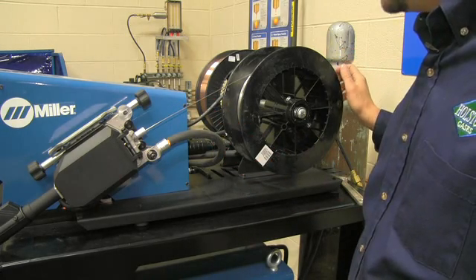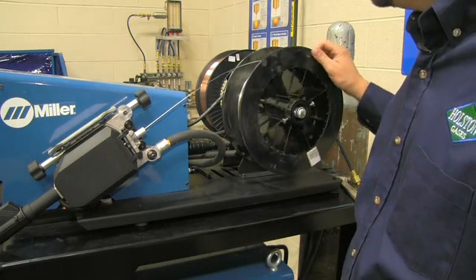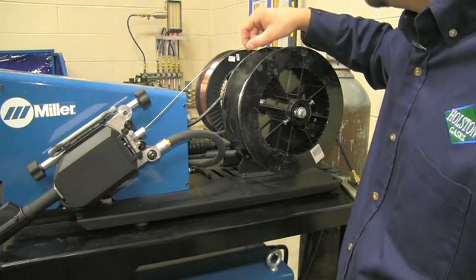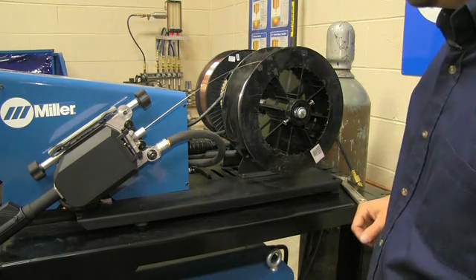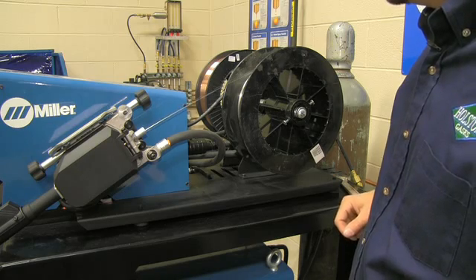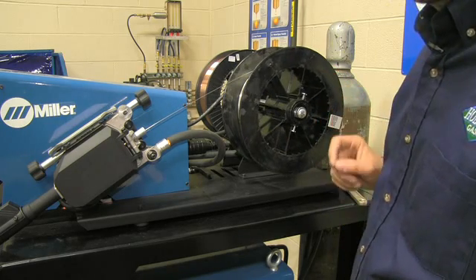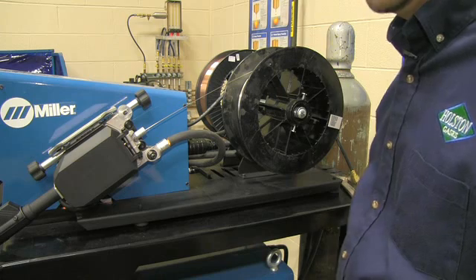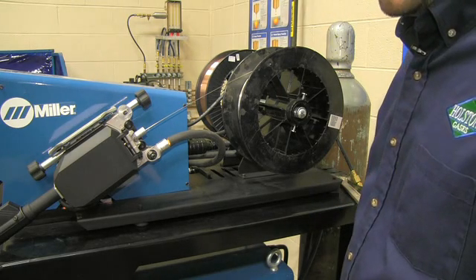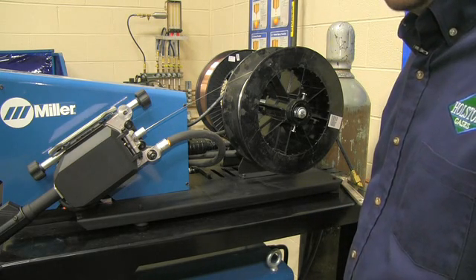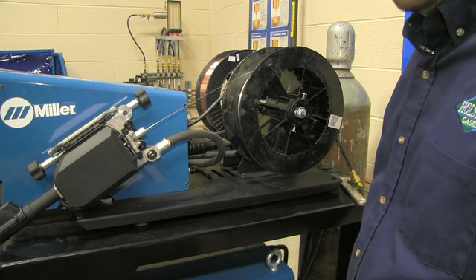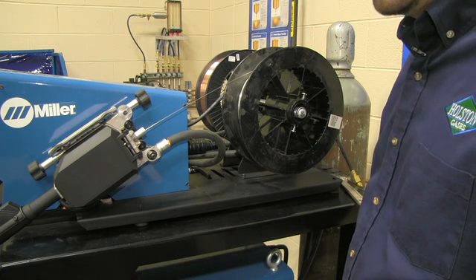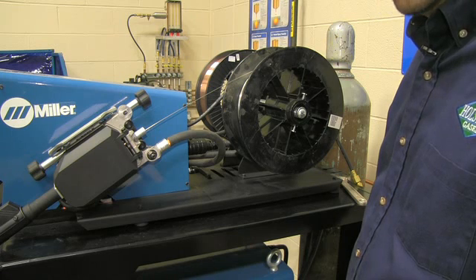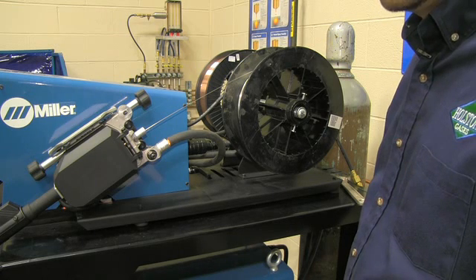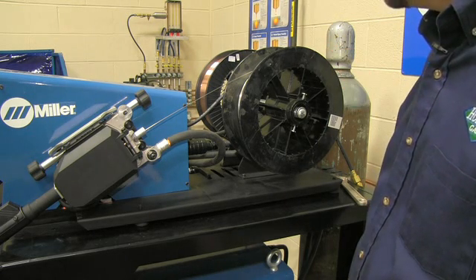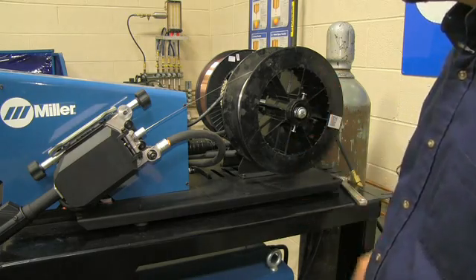So if you can imagine, if we pulled the trigger and then it continued to feed to where there's a big excessive loop of wire here, when you go to pull the trigger again, once it catches up to the drag of the system, it's going to cause a slight hesitation just for a second. Now that doesn't seem like a lot, but if it's severe enough and the wire feed speed is high enough, that can interrupt the wire feed speed just for a moment. And remember, if you're feeding wire at 600 inches per minute, it does not take very much to interrupt that, and that can cause some burn back or just some inconsistent or unstable welding arc. So be sure that your system is set up like this and you'll be good to go.